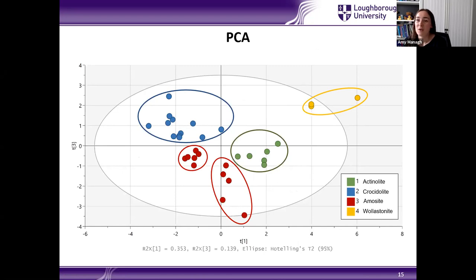When we did a little bit of digging into this, we discovered that amosite is actually present in two different forms. That's grunerite and cummingtonite. And the fibres that we'd been given, we weren't told what type it was. So we strongly suspect that we were actually given a mixture of the two different fibre types. And that's what we're seeing here, separation out into its two distinct forms. Obviously, we would need to do quite a number of additional samples to be able to verify that hypothesis.